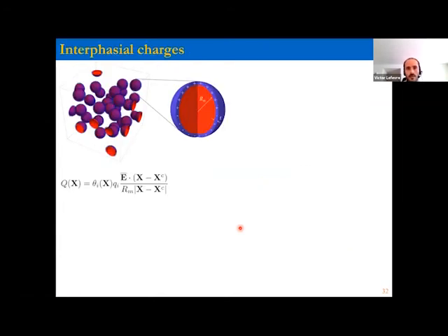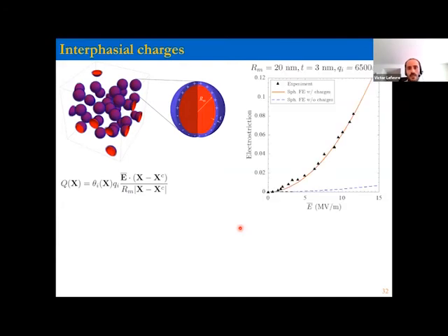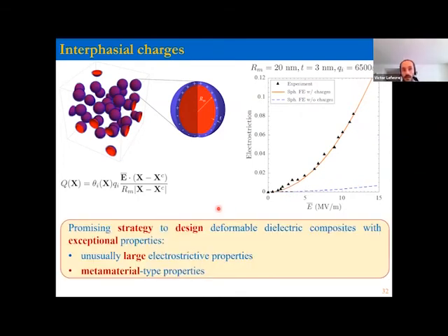So we also did some more calculations now with numerics. So playing a little bit with the numbers that enter in this model, so the radius of the particles, the thickness of the interface, and the charge content. And now with the charges, we are able to get results that are much closer to the experimental data. And again, without the charges, that's the model that we had, the dashed blue line. All right, so this suggests a very promising strategy to design deformable dielectric composites with really remarkable and exceptional properties, because if you can control appropriately the distribution of space charges, you can obtain composites with unusually large electrostrictive coefficients, as well as possibly metamaterial type properties.